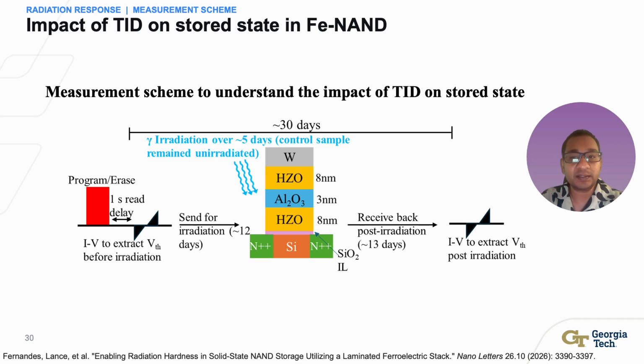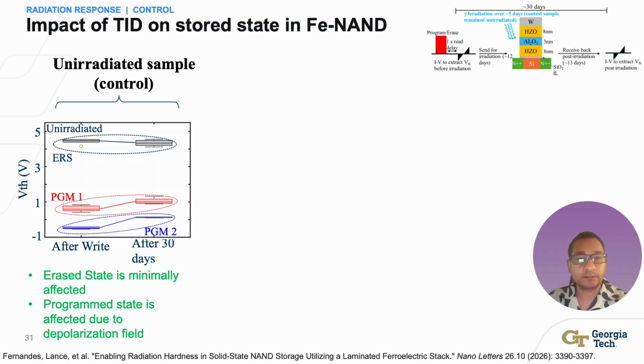The meaningful quantity is not simply the before and after shift, it is the additional shift in the irradiated sample relative to the time-matched control. The control and the irradiated device follow the same handling and waiting schedule. This makes the elapsed time drift a measured reference rather than an unqualified experimental artifact. The unirradiated control establishes that baseline. After 30 days, the erased state is nearly unchanged while more strongly programmed states move towards higher threshold voltages.